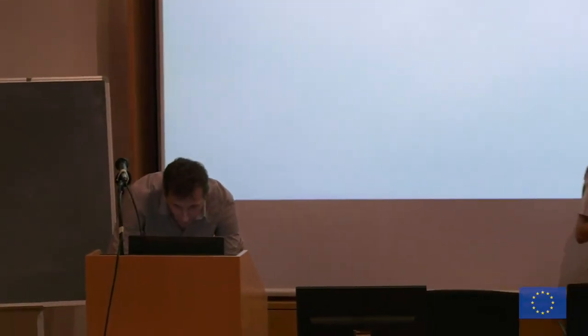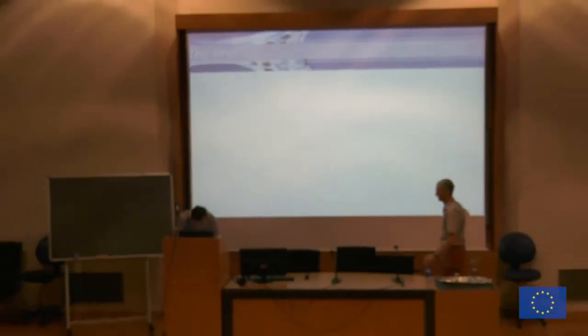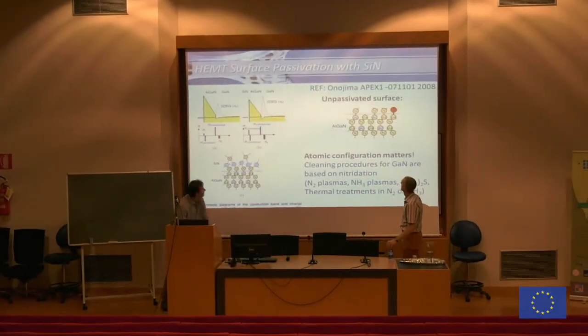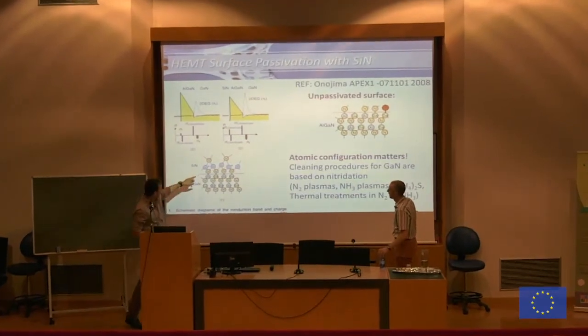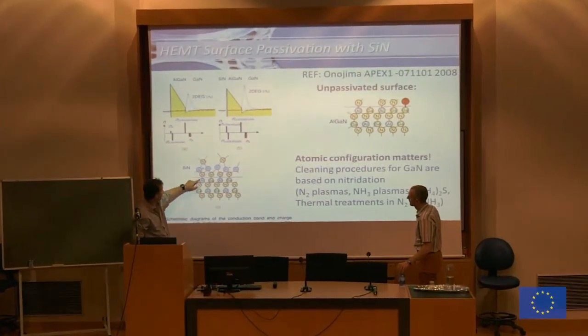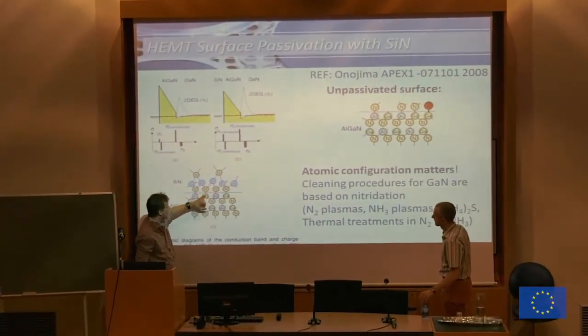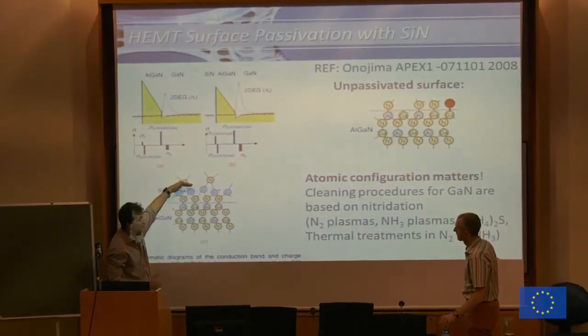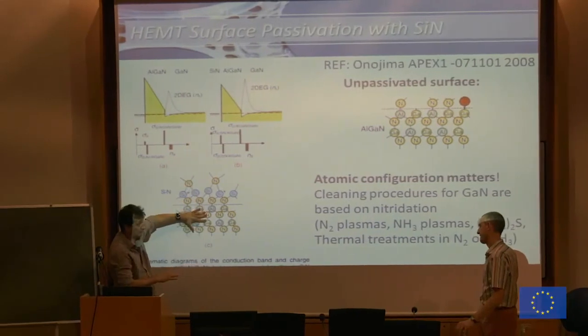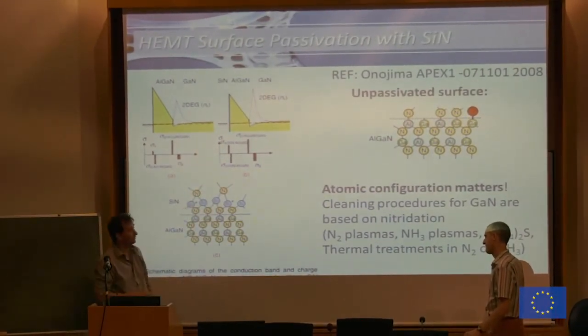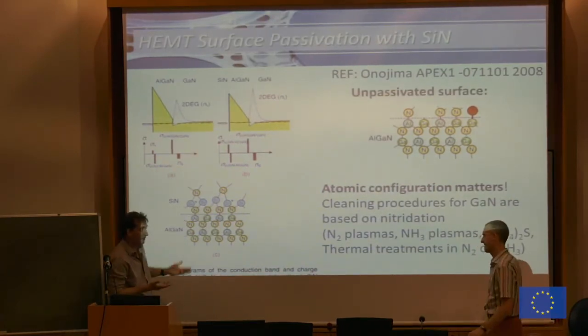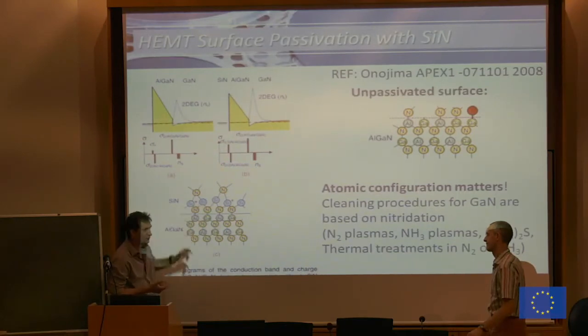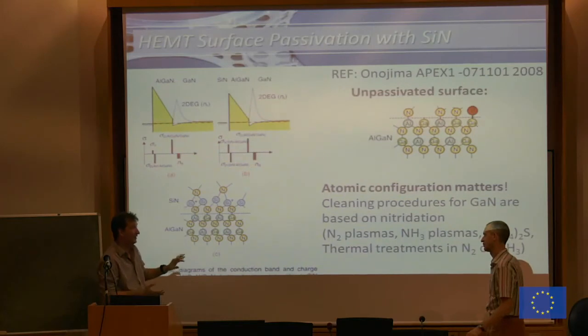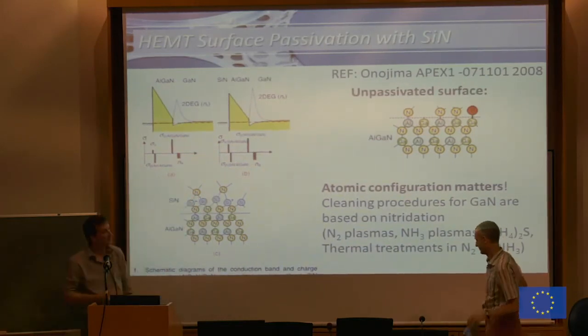No, it would not, because I will go back to the slide. I need to scroll. There, if you have silicon oxide, you're replacing this layer with oxide. So then you will have states, aluminum oxide, gallium oxide, instead of the nitrogens. You can no longer see this as a continuation of the III-nitride crystal. It is then a III-oxynitride crystal. It only works with nitride. Depending, of course, on what the states are, what an aluminum oxide or a gallium oxide do electronically in your band structure. But the way this really works is because you can consider it as the same crystal.